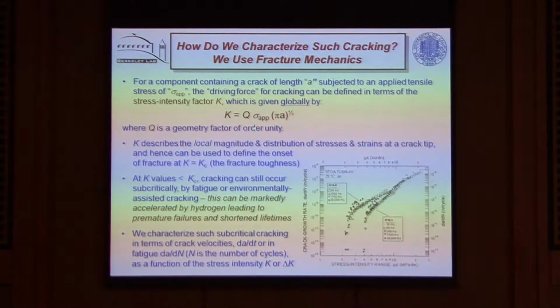This is K. It's a function of the stress times the square root of the crack length with some geometry factor in there as well. And this defines the intensity of the stresses and displacements ahead of that crack tip, and as such can then be used to correlate to the onset of fracture. We can correlate the value of this stress intensity to when fracture can take place. And we can also correlate this term to the velocity at which cracks can grow. So it's a quantitative means of examining from a continuum perspective when and how fracture takes place.